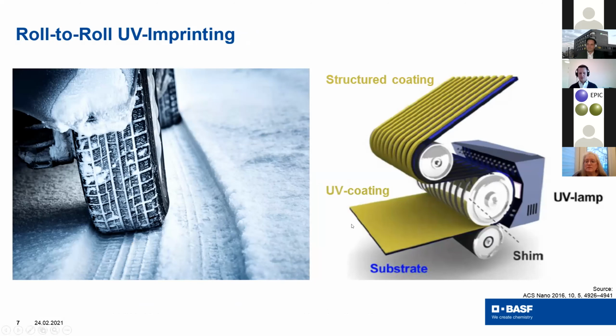Here on the right, you have, for example, a foil substrate, which can be PMMA, polycarbonate, PET. You put a liquid-like UV coating on top. You press it against a pre-structured drum, which was also very nicely shown in the movie before of Fraunhofer. I really liked the movie. When you fill the cavities of this pre-structured drum, you can cross-link the coating with a UV lamp, so polymerize the coating, so it's hard. And then you can demold it, and then you have a structured foil. Sounds very easy. Sometimes it is. Most of the time, it's not that easy.